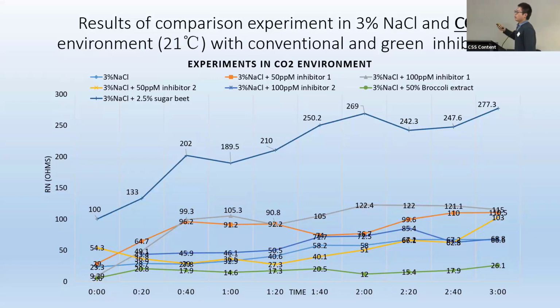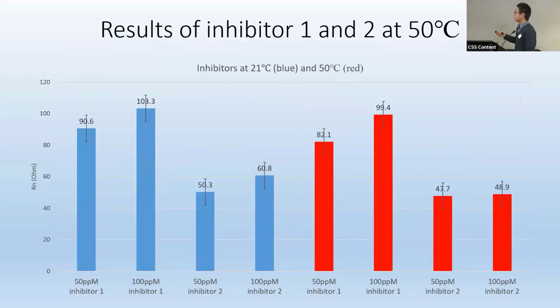I was guessing they were probably designed for higher concentration, higher temperature and higher pressure environments, not for room temperature. So I increased the temperature to 50 for these 2 inhibitors; the blue one was obtained at room temperature, and the red one at 50. And you can see for the 2 inhibitors, it didn't change much between room temperature and 50 degrees. However, you can find inhibitor 1 did better than inhibitor 2 in both cases, and the more concentrated solution did better than the lower concentration.